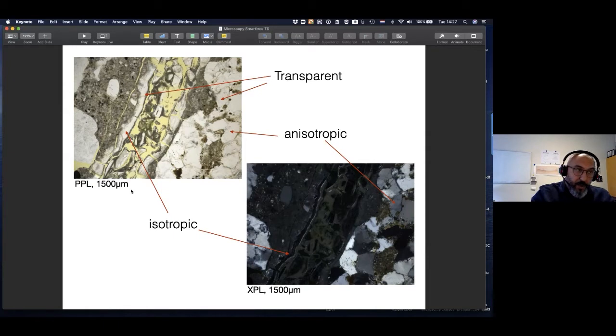Some more examples. You are here observing a crack, for instance, filled with a lot of secondary products. And you see in plane polarized light, you remember I was seeing the natural colors. And all these white deposits here, they are all alkali silica reaction gel, or maybe up to a certain degree, some crystals are also here. So how can I understand, or how can I say, is this a gel? Is this really glassy alkali silica reaction product? The only way to see is to identify if it is an amorphous structure or if it's a crystalline structure, because I know that ASR gel is